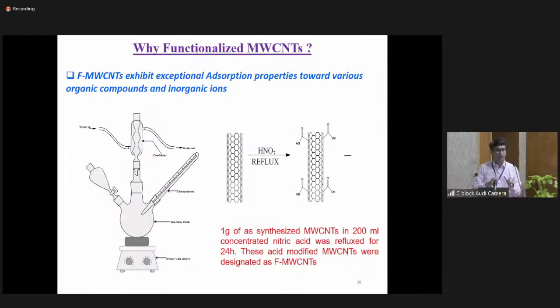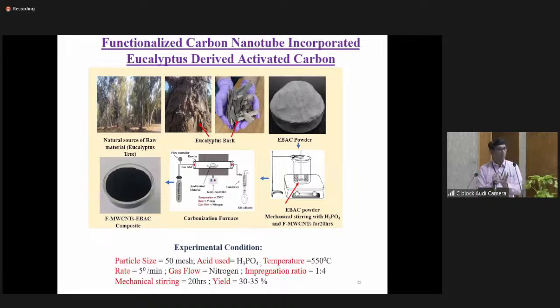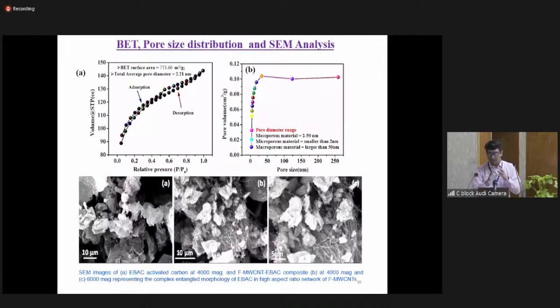After that, what we tried to do, initially the carbon nanotube was not functionalized. When you are producing these carbon nanotubes, big bundles form. So if the individual carbon nanotubes are not incorporated, the property will not be enhanced. When you have functionalization of carbon nanotubes, the individual carbon nanotubes will be there, so that the property can be further enhanced. So accordingly, a similar process was followed, only the carbon nanotube was replaced with the functionalized carbon nanotube. Then surface area was also enhanced, between that of the pure activated carbon and the carbon nanotubes. It's around 700. And then pore size was further reduced to 2.2, very close to the diameter of both the dyes.